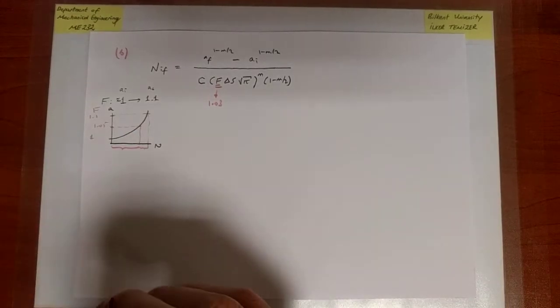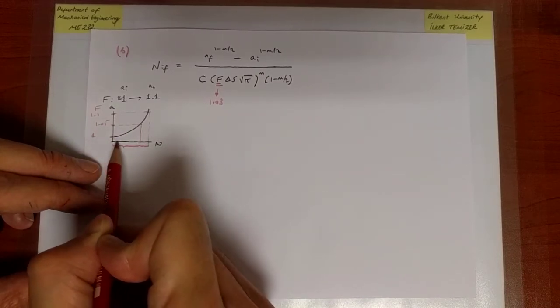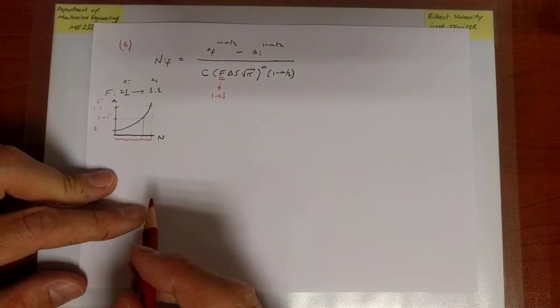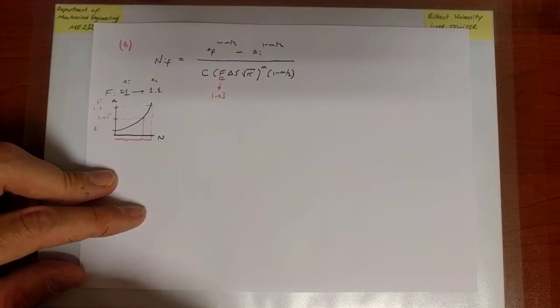Okay, well, why not 1.04? That's also fine, but the point is the midway is 1.05. The crack spends more time in the region that is less than this midway value, and so you take a value that is less than the midway value. In this case, I took it to be 1.03. So we're going to take f to be that value.